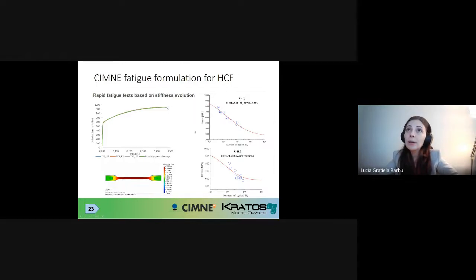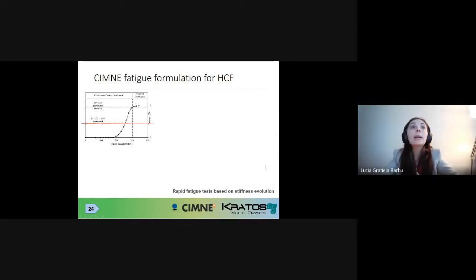Then we also calibrated our fatigue parameters for the -1 and for the 0.1 curves. And then we proceeded to evaluate if we obtain the same behavior after doing this rapid loading history with the blocks of cyclic load.